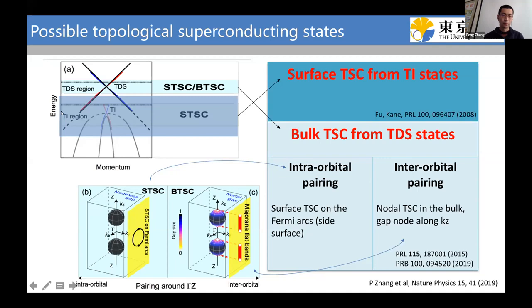If we can shift the Fermi level, for example, if the Fermi level is located near the surface Dirac cone, then the physical properties will be mainly dominated by this surface Dirac cone. If we shift the Fermi level to the bulk Dirac cone, then the physical properties will be mainly dominated by the bulk Dirac cone. If the Fermi level is located near the surface Dirac cone, then in the superconducting state, we will have surface topological superconductivity according to the Fu-Kane model.